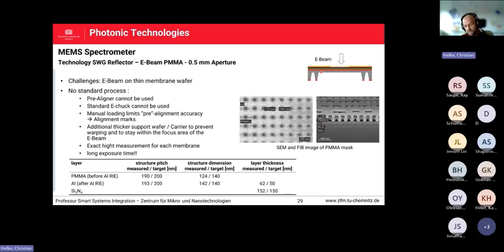This has some drawbacks for our e-beam itself, so we cannot use the pre-aligner, which is very necessary if we want to do layer by layer alignment. We could not use our standard e-chuck for exposure in the tool itself, and some other points, but in the end, we could resolve structures in the range of 125 nanometer, as you see here, for example.